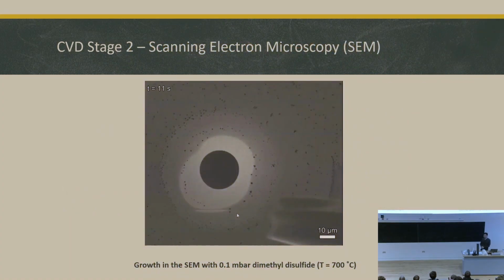So once we have this metal precursor, which is tungsten oxides, we want to introduce sulfur because we want to build this sandwich-like materials, 2D materials. So we introduce sulfur by injecting the gas phase of dimethyl disulfide at 700 degrees C on the same halo spot. Let's see what will happen once we introduce sulfur.